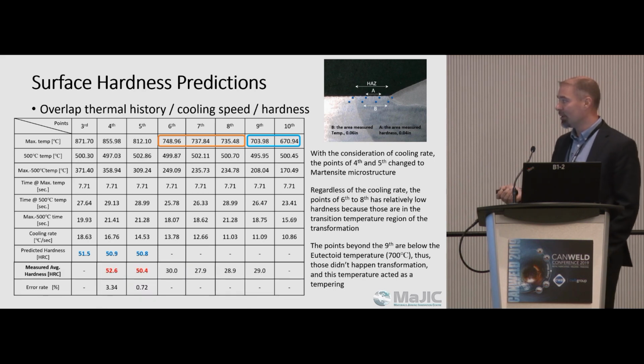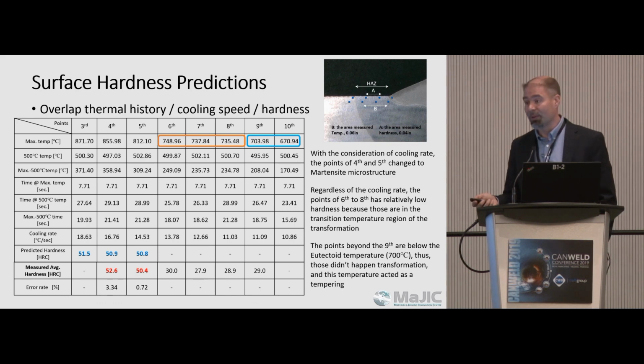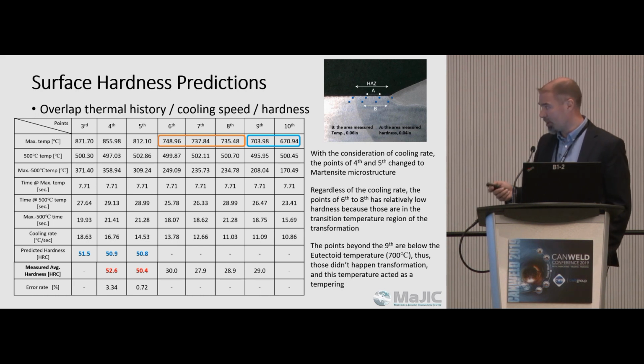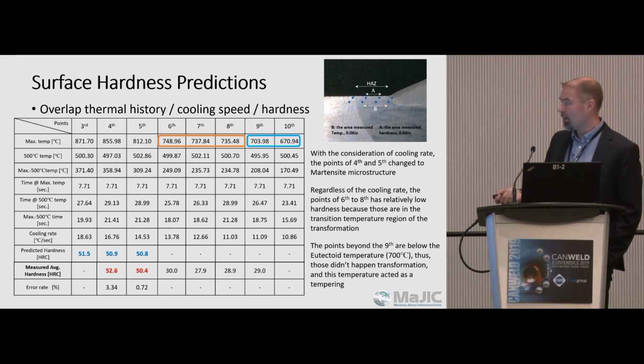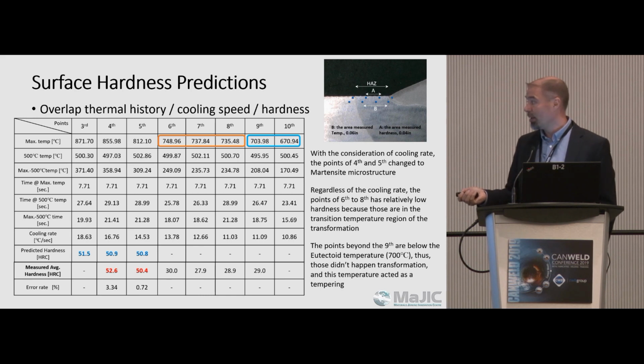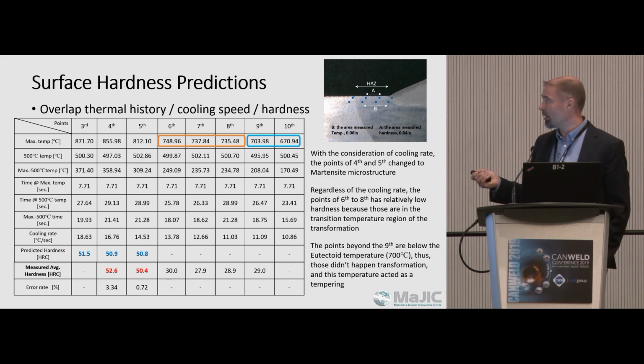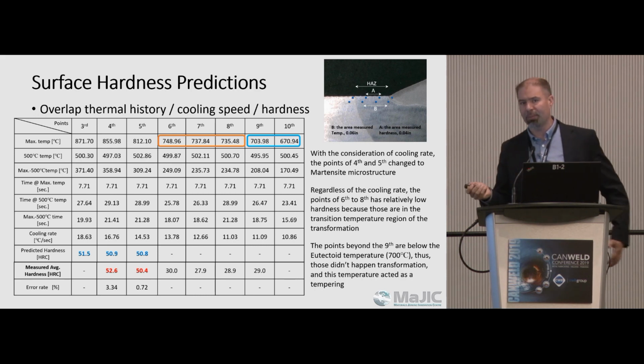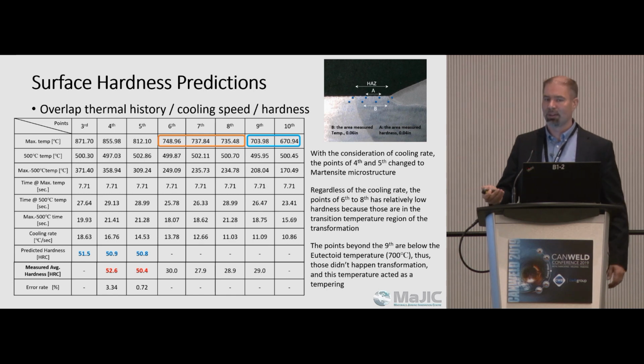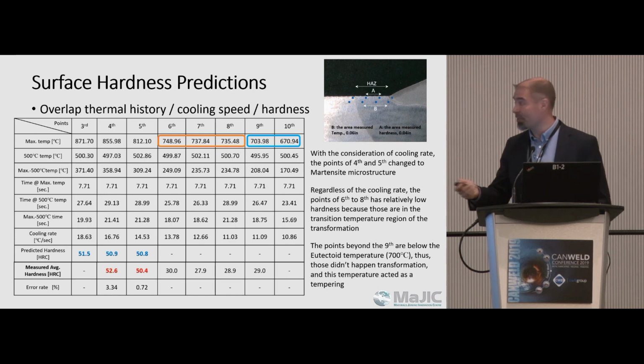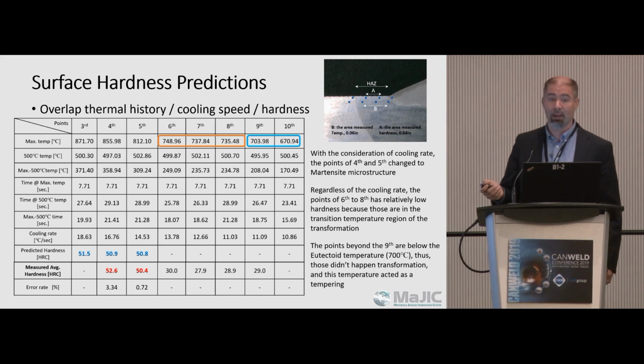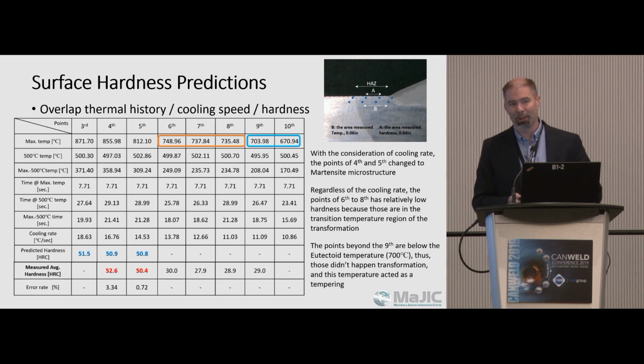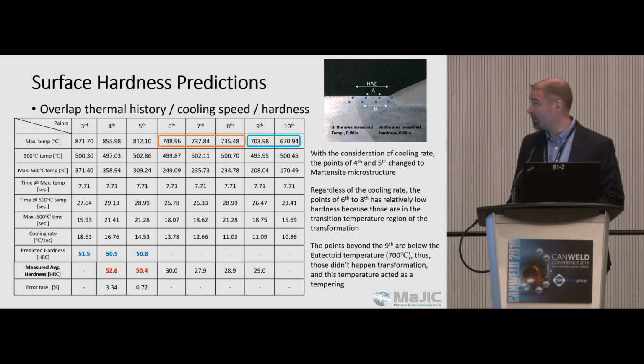So the actual hardness in these areas was very close. So we're pretty happy with the initial results here. Less than 4% error on one, less than 1% error on the second point. The initial point here, right on the fusion line, we weren't able to measure that accurately because of the interference with the weld. So next steps, we're going to end up just machining that weld cap off nice and flat and going from there. But we'll talk about next steps shortly.